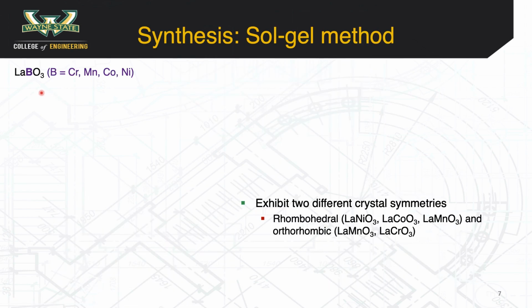We start off by studying n equal to infinity type perovskite oxides because these have been widely studied for electrocatalysis. We choose lanthanum as the A site because of its high electronic conductivity amongst the rare earth metal oxides, and the B site is varied all the way from chromium to nickel amongst the 3d metals due to their cost effectiveness. In addition, varying the B site metals from chromium to nickel gives us an opportunity to study the effect of crystal structure as it varies all the way from rhombohedral to orthorhombic symmetry.